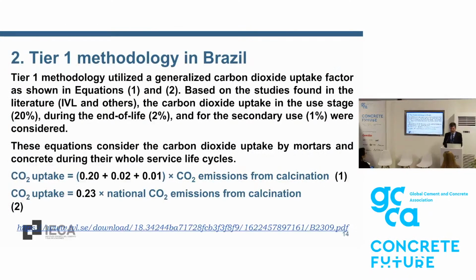Okay, well, this is the simplest method, as we can see. Also it is very conservative because only 20% of the calcination emissions are considered to be absorbed, uptake by the concrete or mortars. The equation is, as we can see, and also Claude explained before, that 20% of the calcination or the carbon dioxide emitted during the process are considered to be uptake. Then 2% of these emissions are uptake during the final of the service life of the structure, and finally 1% can be considered to be uptake in the secondary use. At the end of the day, this is 23% can be absorbed by the cement-based materials.